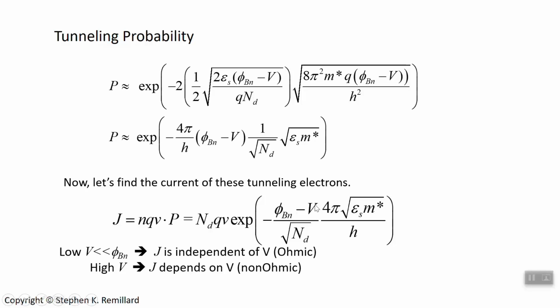If the voltage is very low, V is a very small number, then it's being overshadowed by the Schottky barrier potential and it doesn't affect anything. So the voltage basically disappears from this exponential when it's small. But when voltage is small, the current is depending linearly on voltage through the velocity only. But now when the voltage is high, your current has this complex relationship. It has this exponential of voltage, and that is very clearly non-ohmic or non-linear.